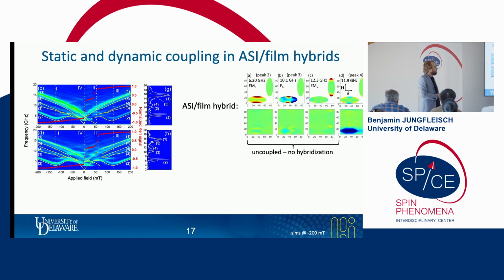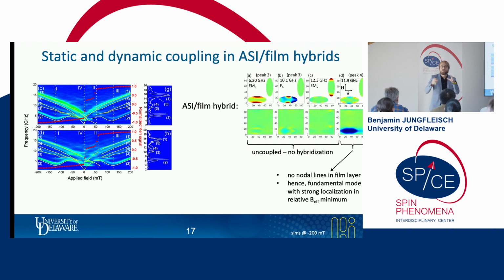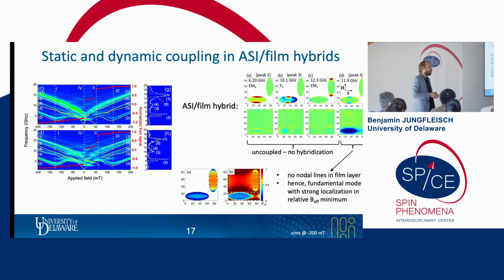Now there's a different mode here. This is mode number 4. And here we see that there is some precession, there are some oscillations in the film. This has no nodal lines in the film layer. This is the fundamental mode with a strong localization in the effective field minimum. So it's essentially like a well. And I'm showing here the effective field in this plot on the left-hand side. And you can clearly see this local minimum underneath the horizontal elements. So the dynamics are basically trapped in this well, and this allows us to excite dynamics even below the FMR, below the Damon-Eshbach frequency.